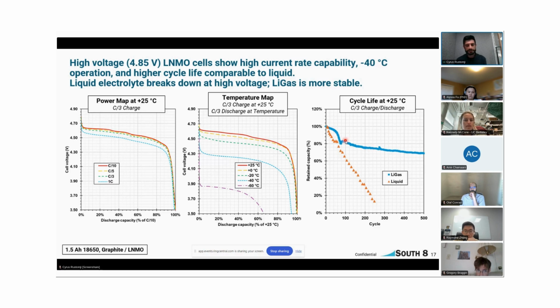We have this quick drop down to 80% discharge capacity, but then it levels out thereafter. Internally at South 8, we're better understanding what this mechanism is, and we have identified some paths forward, which we are currently developing. But the fact that we see this really nice plateau over here, where it's relatively stable, just tells us that these liquefied gas electrolytes are more inherently stable than your liquid counterparts.